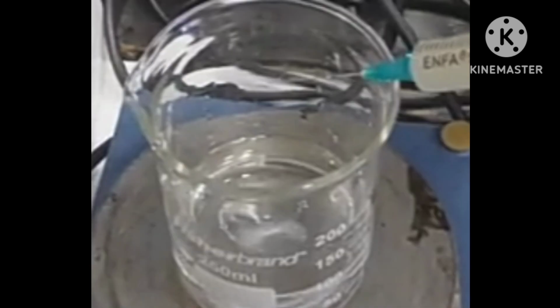One of the major drawbacks of the self-healing paint that was first made is that it requires stress from the crack for the healing agent to be released. There must be a crack. One of the important factors used in developing the microencapsulation for the emulsion paint, which is known as water-based paint, is that the coating thickness was ensured to be larger than the microcapsule size, just like the picture you saw in the beginning of the video for wood coating.